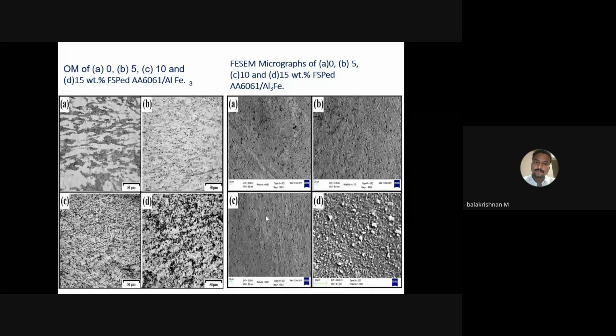Here we can see some agglomeration of particles. This is due to the higher number of intermetallic particles, which will totally demolish the formation of dendritic structure. So in this image, we can observe that complete refinement of the cast composite has happened. In figure D, compared to figure A, figure D was completely refined.